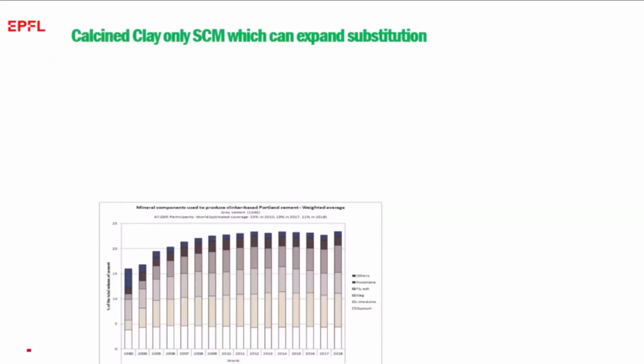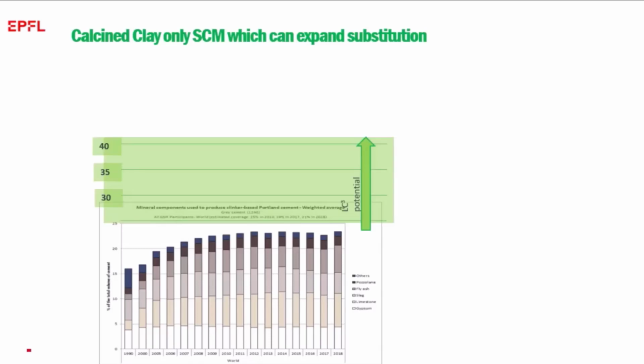So the potential of this is really phenomenal. This graph here shows the average level of clinker substitution around the world according to the GCCA figures, and you see for the last 10, 15 years this really hasn't moved at all. And the biggest substitutes today are limestone, slag, and then fly ash and a little bit of pozzolans. And the reason this hasn't moved is precisely the limitation in the supply of slag and fly ash, as I already pointed out.